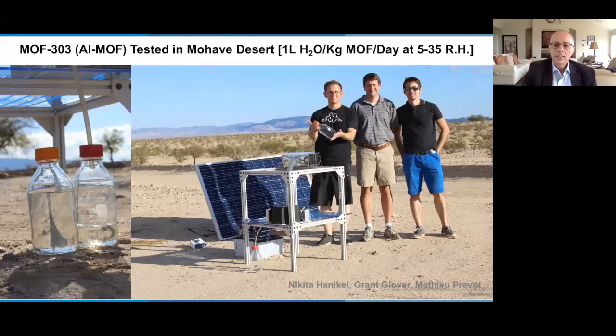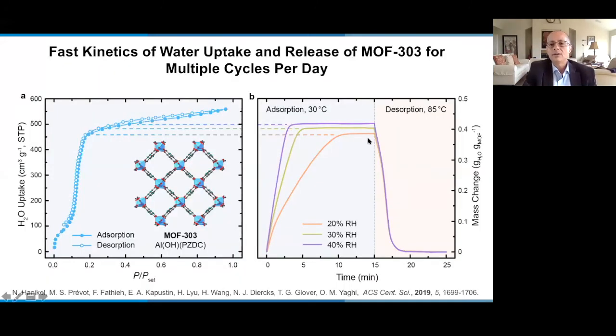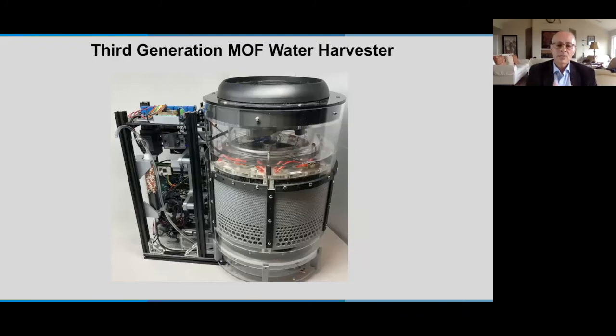Now you're talking about significant amounts of water, and because the release time is minutes, you can do many cycles. Not only can you take it up easily, but it can also be released very easily. And that's the key here: with heating to 60 degrees C or 85 degrees C, you can get the water out in very few minutes, and that means that with a solar panel supplying enough power to run a small fan to push air into the MOF, I can do many cycles of uptake and release. Based on that, we have designed a system that can now do 200, 250 cycles per day.